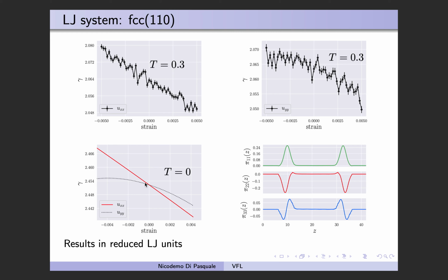By using these results, we can obtain the different components of the Shuttleworth equation, which can then be compared with the surface stress obtained from the pressure profile, which is shown in the bottom right plot.